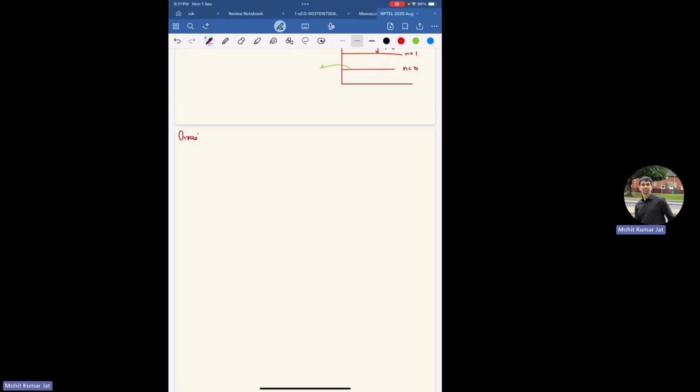Graphene in a magnetic field. In this part, we will restrict ourselves to low energy near the Dirac point, such that the system is well described by the Dirac equation, that is, in the region where energy is h bar k Vf. So all the calculations in this part are performed for excitations near the K point, and similarly for the other valley K prime, these can be obtained in an analogous way.